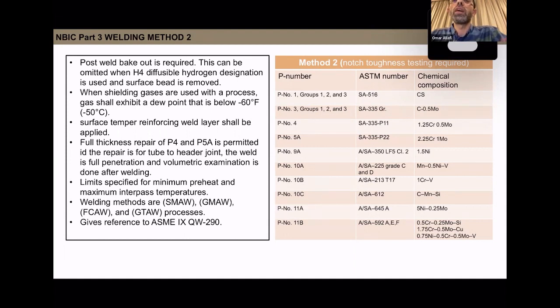Full thickness is permitted only for P4 and P5A material, under certain conditions. This is when the tube to header joint is full penetration, and volumetric examination is done after welding. The reason is that they don't want to permit this technique for all weld joints. They specified the use of full penetration or full thickness repair for P4 and P5A. They limited the use of this technique only to tube to header joints.